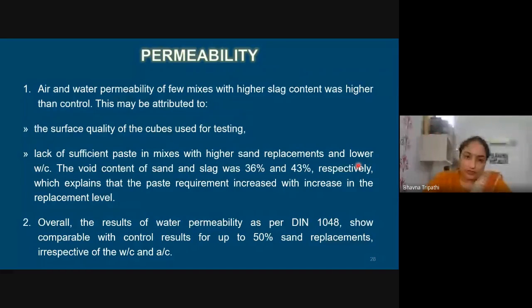Now I will again remind you what I have previously also stated, that as we increase the slag percentage, it affects the paste content, and the paste of concrete gets reduced. So the surface of the concrete cubes that have higher percentage of slag was not very well finished, which had pores, and that would obviously result in higher permeability. Again, this is very true because with the Autoclam permeability apparatus, you have to also look at which kind of apparatus you are using.